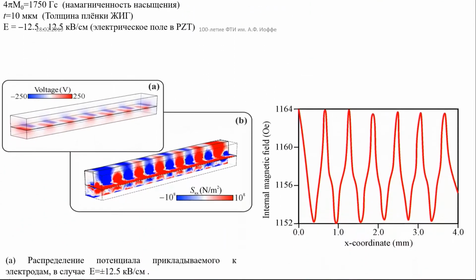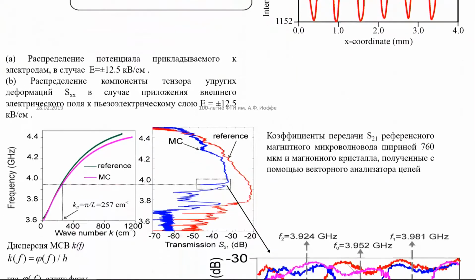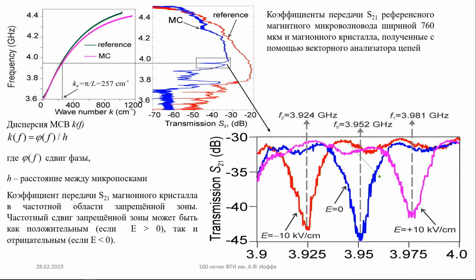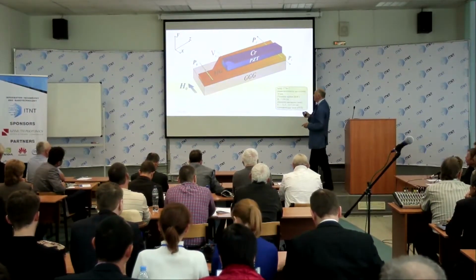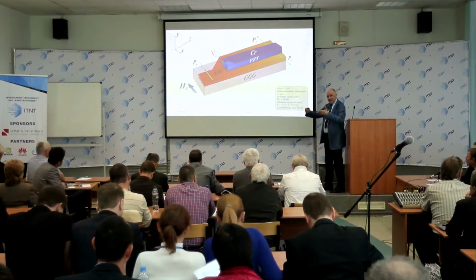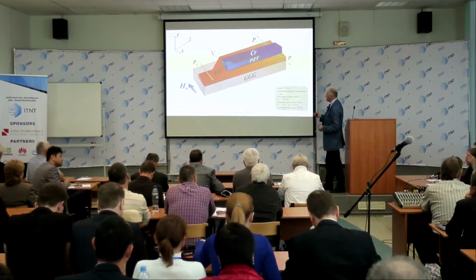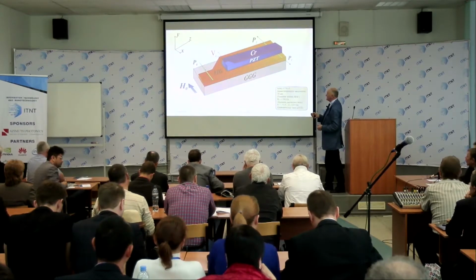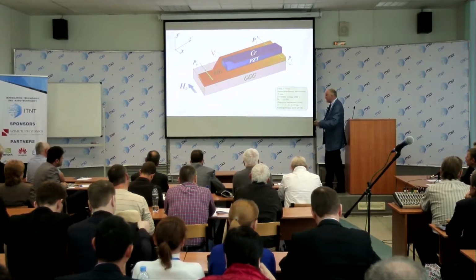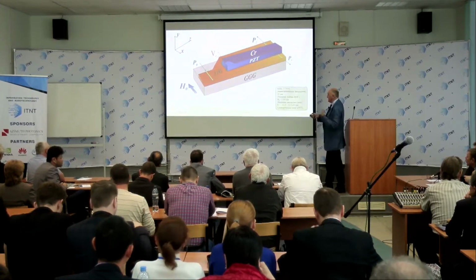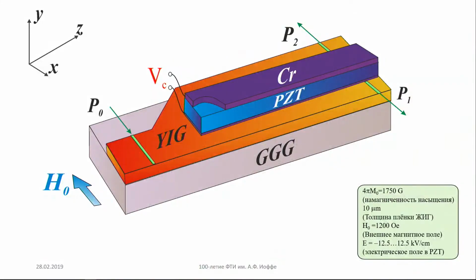So, for example, this is a structure which can be used: yttrium iron garnet is the magnetic material, PZT is a ferroelectric material, and chromium is for excitation of current. This current changes the properties of the ferroelectric material, and it in turn changes the properties of the yttrium iron garnet and the properties of the propagating spin waves. Therefore, we can govern the propagation of spin waves without any external field, for example, by pure spin current in material which is connected with magnetic materials.